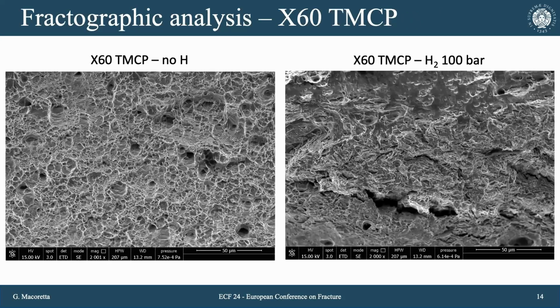The same happens with the TMCP material, which has a somewhat more ductile surface in the hydrogen-free condition. When we have hydrogen in the material, we observe transgranular fracture. We can also observe some tears, and in proximity of the tears, some pseudo fisheye features that hint at some hydrogen accumulation in those places. So there is a deeper, localized embrittlement effect of hydrogen.